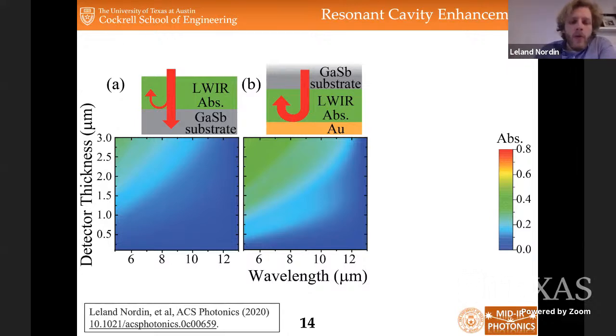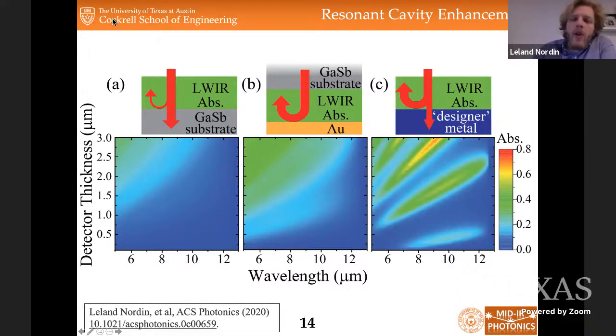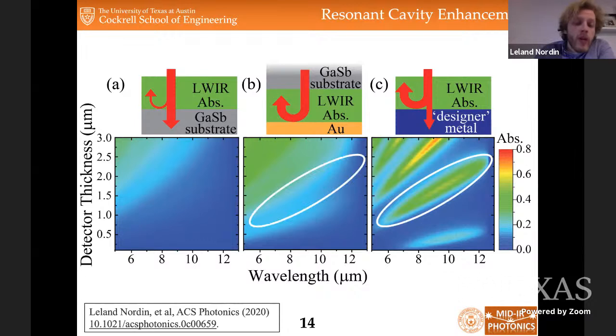So what about if we grow one of these on top of our plasmonic ground planes? Well, you can see that we are able to form a resonant cavity with the air, semiconductor, highly doped semiconductor ground plane, and we can get rather significant enhancement of absorption in the long wave infrared, around 8 to 12 microns, something that we do not see in the double pass configuration. And then I'd also like to note there's this even thinner first order Fabry-Perot mode, around 300 to 500 nanometer absorber thicknesses, that we could leverage to actually couple into surface plasmon polariton modes, and I'll talk about that a little bit later.